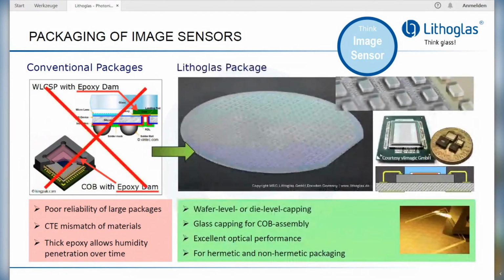For this, we have wafer-level or die-level capping technologies. On the wafer-level technology, we add glass lids which actually have a glass dam. So there is no glue or whatsoever, just a small cavity on the optical sensing part. But underneath the dam, there's a very thin glue line, allowing for higher reliability. And this can be done for very small components, where many components are attached at the same time, the glass lid being smaller than the chip but the bond pads still free to make chip-on-board packages. And it can be done for large components like this image sensor you can see here.